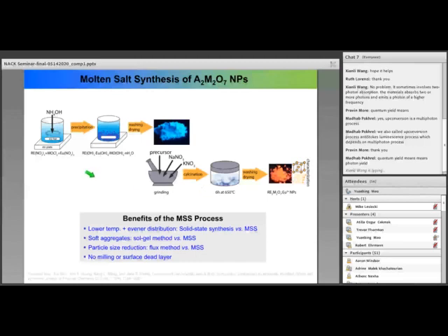The dopants, how evenly they are distributed in the host materials, that's also very important, because we really don't want to form clusters of the activators. Once that happens, right, when the activators form clusters, then they will have the concentration quenching much earlier than it's supposed to. So that's why this is very important.